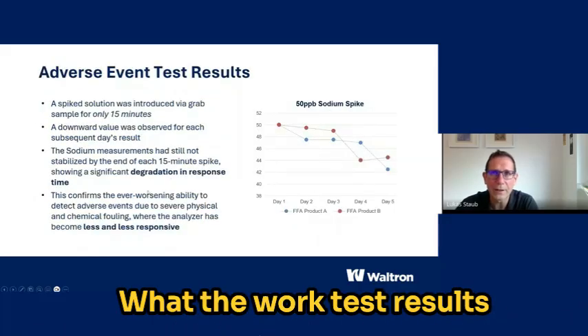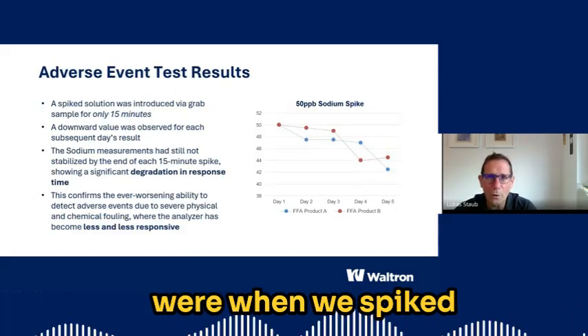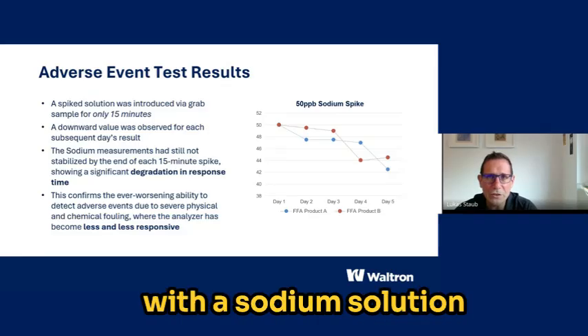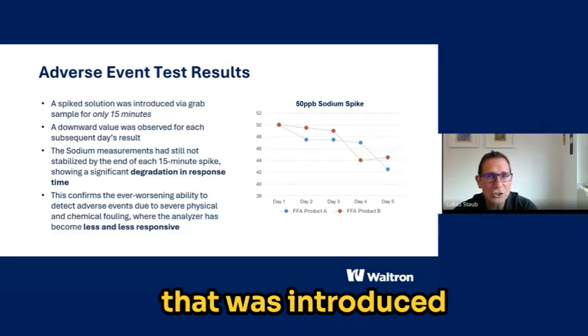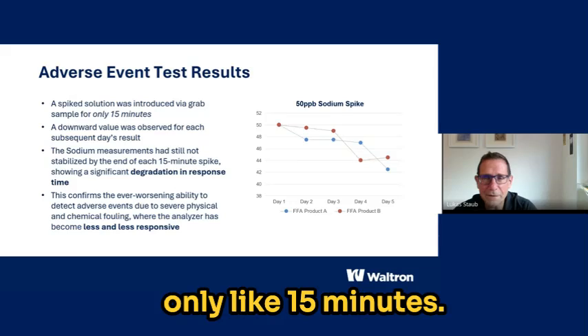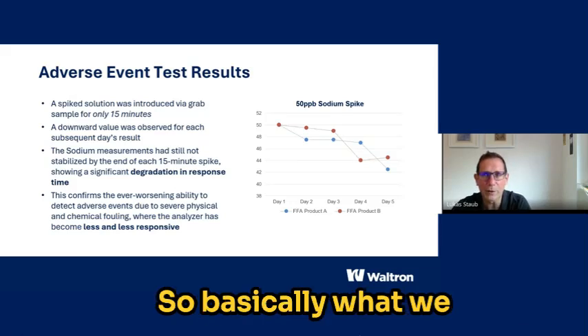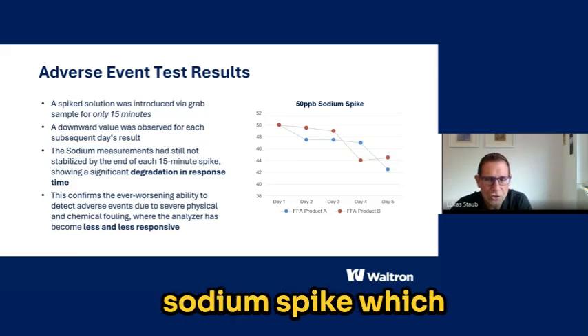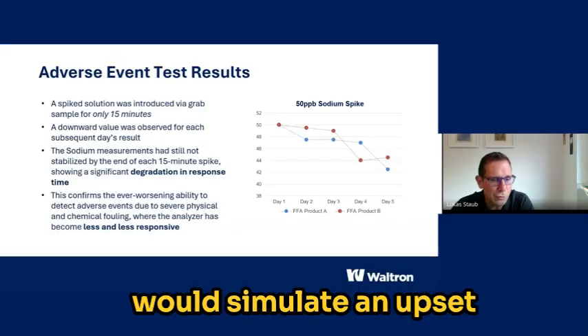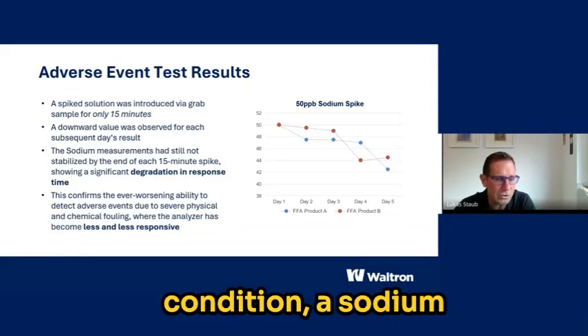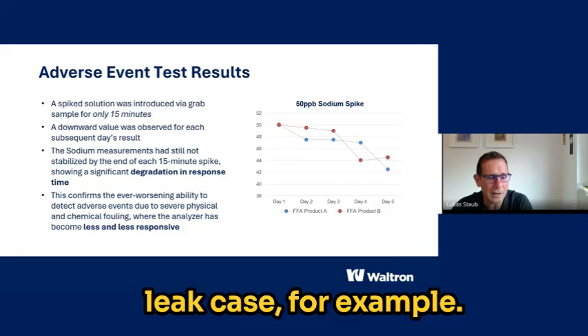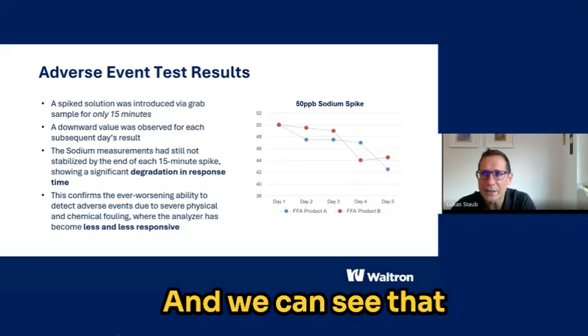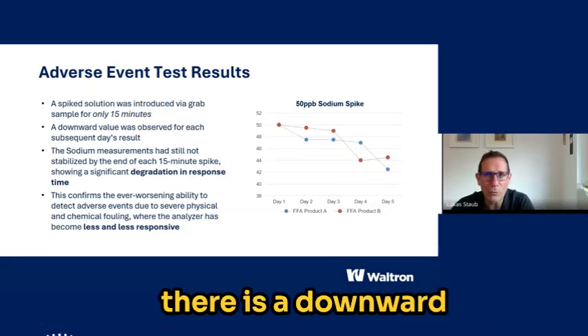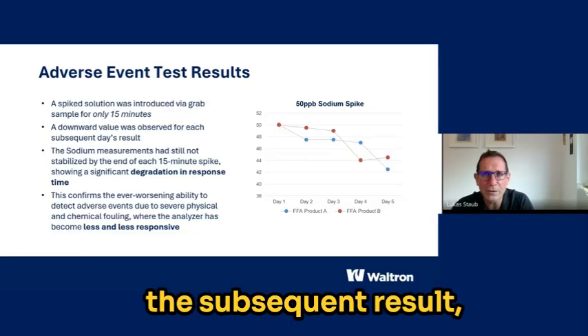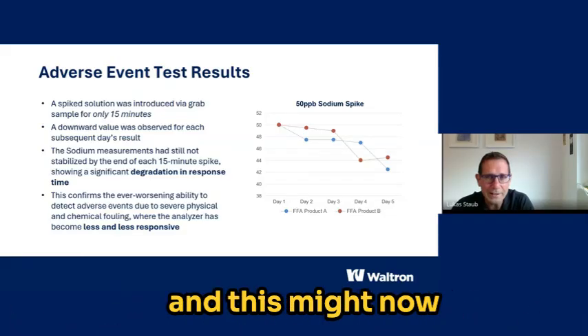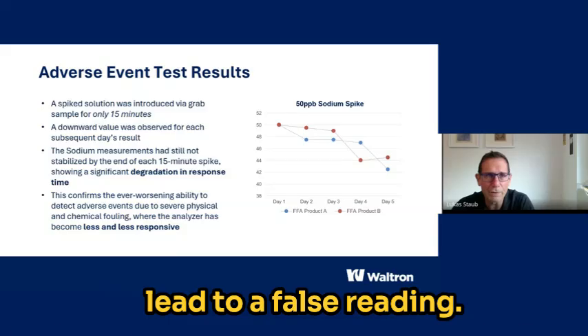What the test results were when we spiked was a sodium solution that was introduced by a grab sample for only like 15 minutes. So basically what we did was injecting a sodium spike, which would simulate an upset condition, a sodium ingress in a condenser leak case, for example. And we can see that there is a downward trend value observed for the subsequent result. And this might now lead to a false reading.